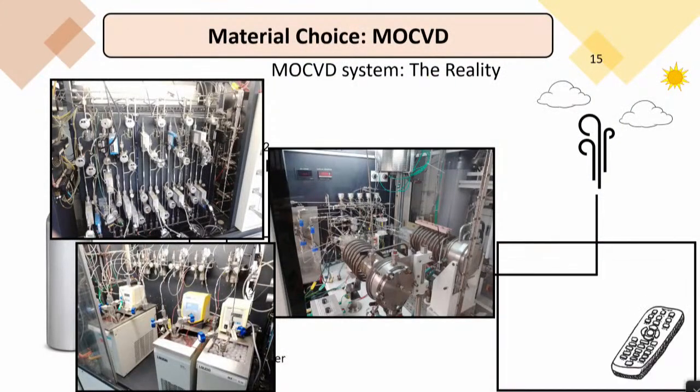These are the reactors. We have two for growing different materials. In one reactor, we only grow cadmium oxide because these systems have a very good memory, and if you put something else, the next crystals you grow will have this material even if you don't want it.